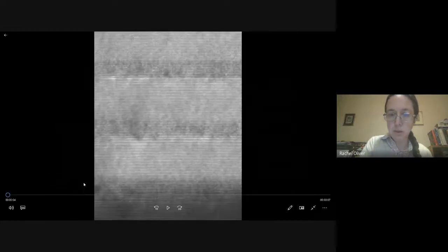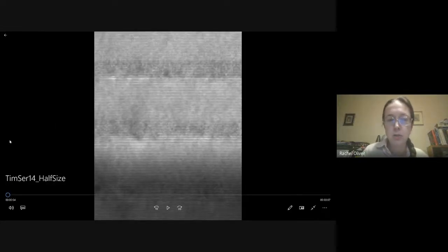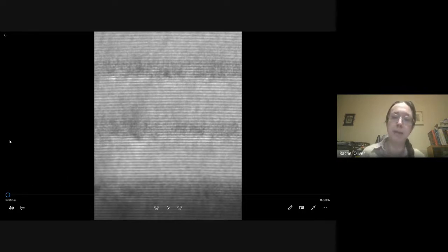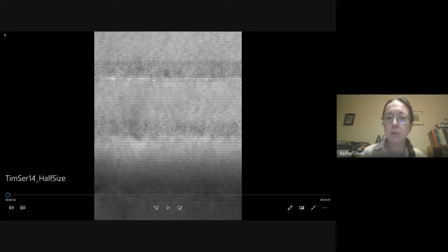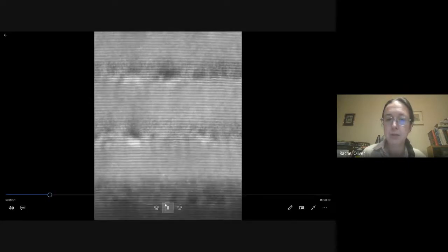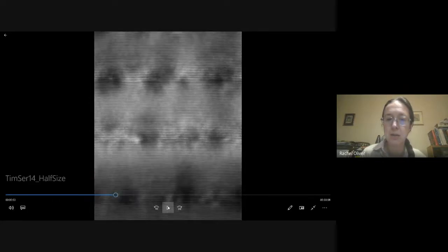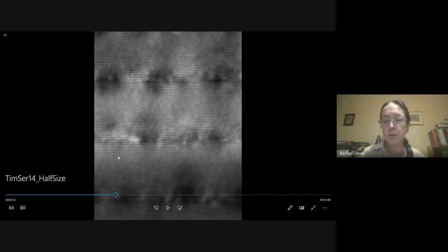here we go. Okay, so this image I just showed you is actually the first image in a sequence, a video, where we've kept the electron beam in the electron microscope on these quantum wells. Now you can see these quantum wells look maybe slightly blotchy in places, but basically fairly uniform. But as we expose them to the electron beam over time, they change. So that what we've got now, after a couple of minutes of exposure to the electron beam, we can see that now our quantum wells look all blotchy.